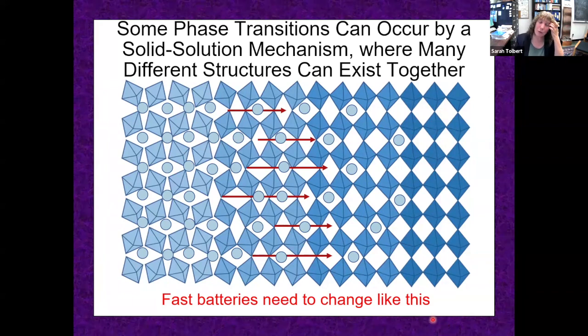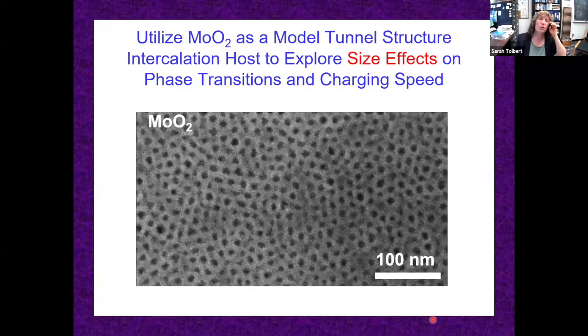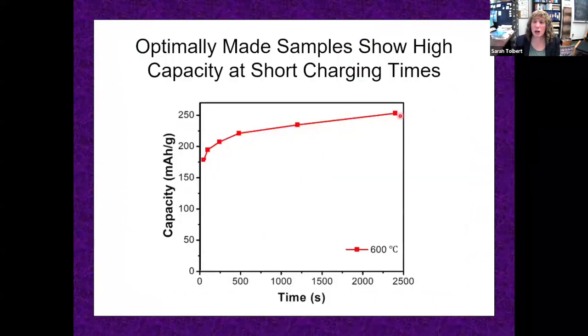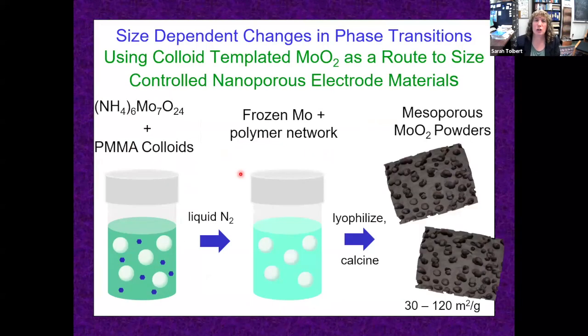So let's look at some real data and see if we can convert a battery that is slow to a pseudocapacitor that is fast. So the first system we're going to look at is molybdenum dioxide. This is a tunnel structure material, so it's not layers, it's tunnels. But it has the advantage that it is a metallically conducting oxide. So electrical conductivity is not a problem. And we're going to use it to explore size effects. So this is an electron micrograph of a porous moly oxide phase. And when we try to charge this material, what we find is when we charge it faster and faster, so this is charging time, getting shorter and shorter, we hardly lose any capacity. So we said, okay, this is a good model system that might be a fast charging battery.